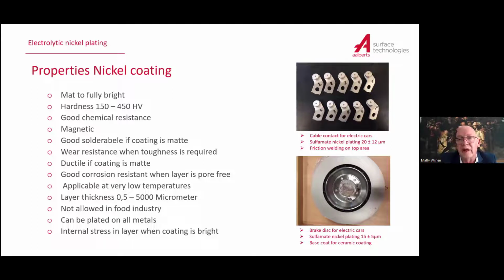And what I said about friction welding, you see on the right side the picture of these contacts, where the tops are friction welded onto each other. Friction welding is a welding system where you move the parts over each other with very high frequency, without any helping metals. The nickel part is welded onto the nickel part on the other side. You have a very good welding system, which doesn't need any extra chemicals to make sure welding takes place. Cable contacts for electric cars are used a lot at this moment.